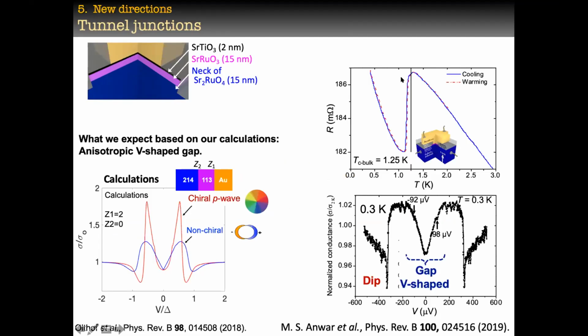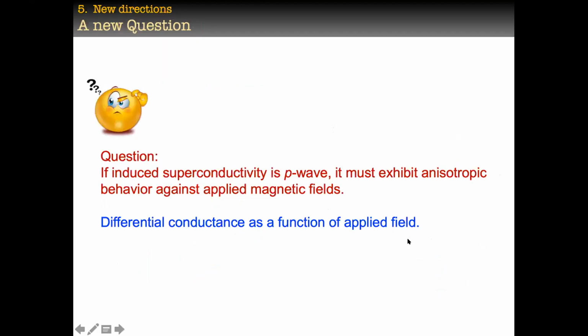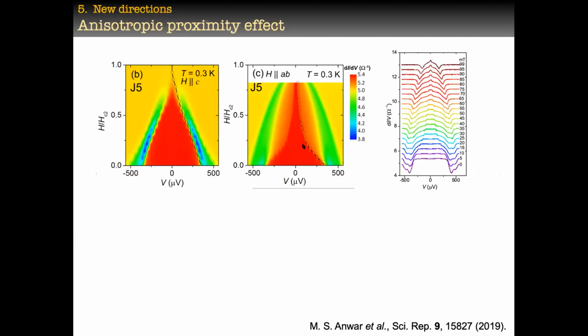And then these devices show again a superconducting transition beautifully. And then you can see here it is exactly the V-shaped differential conductance, which is experimental. So it shows it is a spin triplet. So if it is a spin triplet, then you can ask the question of whether it has some kind of anisotropy, like a magnetic anisotropy. Let's have a look. Yes, these are the color pictures. Color picture means the function of applied field. When I apply the field along the C-axis, the order parameter is suppressed in the normal way that we expect with the increase in applied magnetic field. But when I apply the magnetic field in plane, along the AB plane, then you can see that first it's suppressed strongly, then slowly.